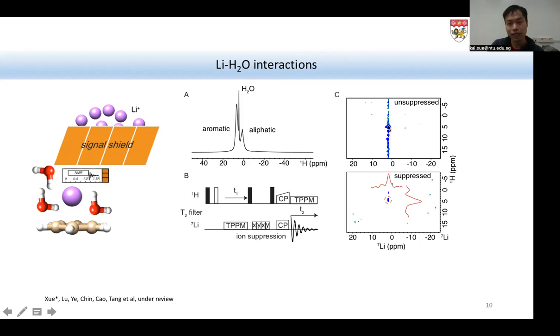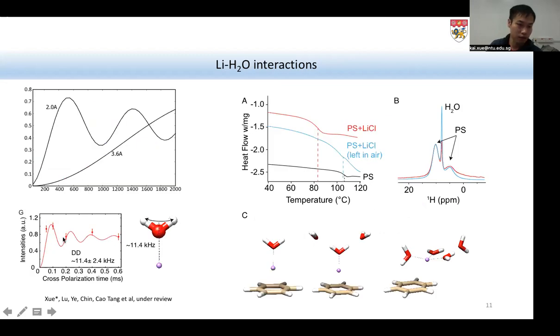So in order to have an analytical analysis of the peak intensity, we need to suppress this T1 noise first. Here we repurpose a scheme, the MISSISSIPPI pulse sequence, from solvent suppression and add it here for the aim of ion suppression. Normally for solvent suppression, we need 100 milliseconds to 300 milliseconds as the length. But interestingly, for ion suppression we need approximately 1 second in order to fully suppress these ion signals. As you can see on the right side here, with the addition of this ion suppression block in the pulse sequence, we have a clean peak only. So with a clean spectrum, we can analyze the signal buildup due to CP.